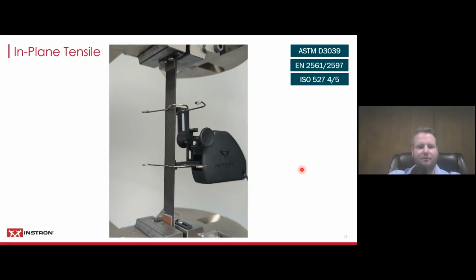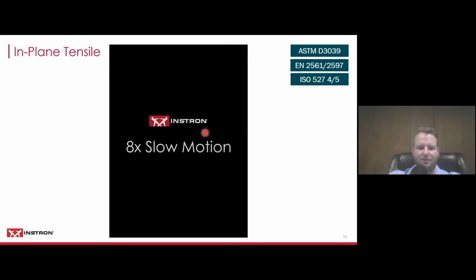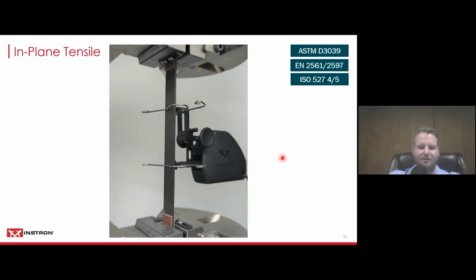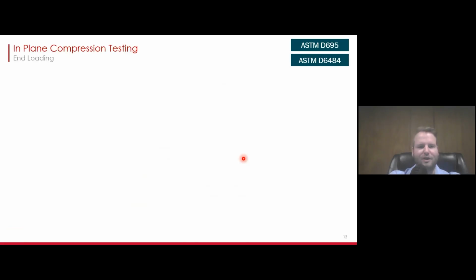Here's another video of a typical in-plane tensile test. And you can see here, we're going to slow this down a little bit. And you can see there's even sparks flying from the knife edges of the extensometer when the specimen explodes, and then the extensometer kind of goes flying and the knife edges rip along the specimen. So very hard surfaces and very challenging to record strain, as you can imagine, with these kinds of materials. But nonetheless, very spectacular breaks.